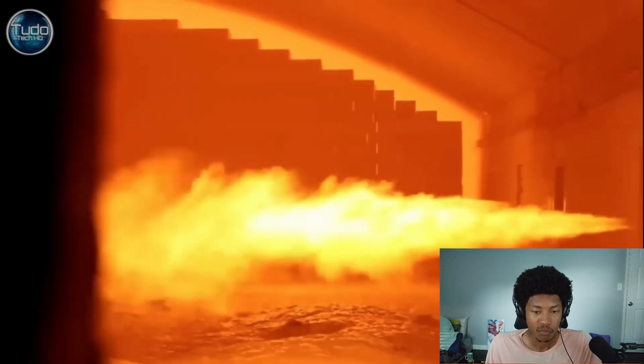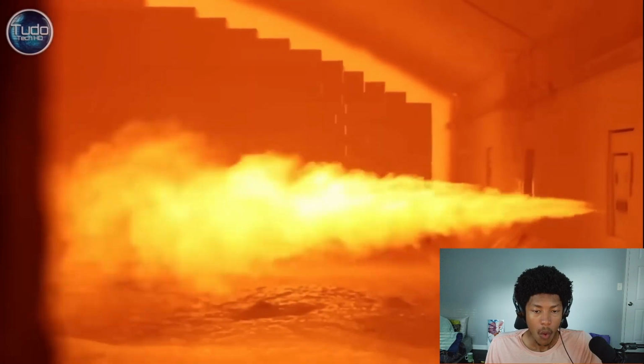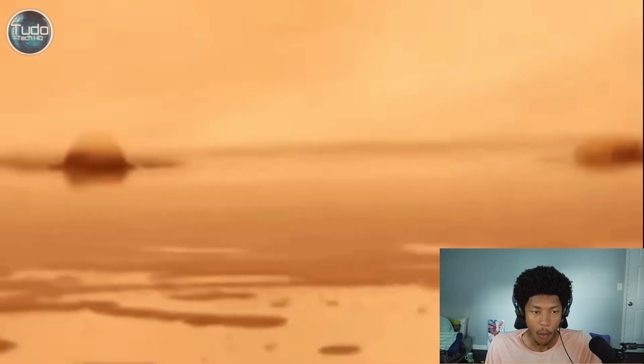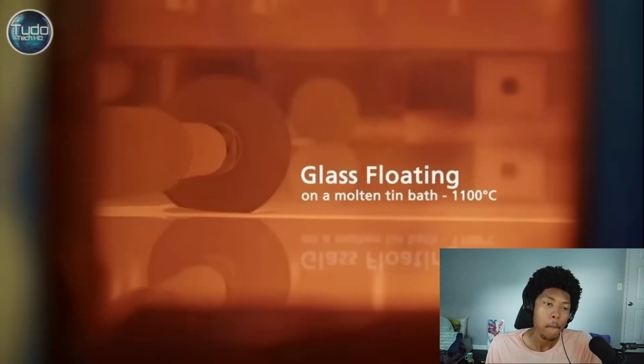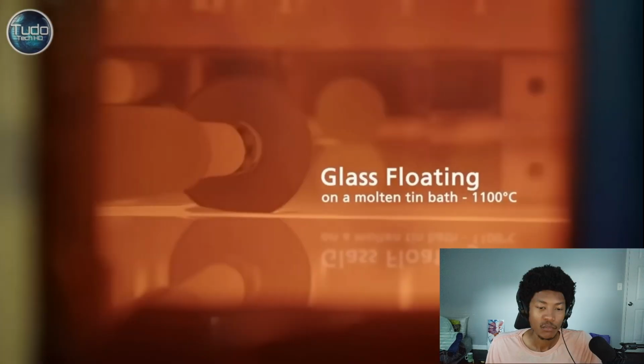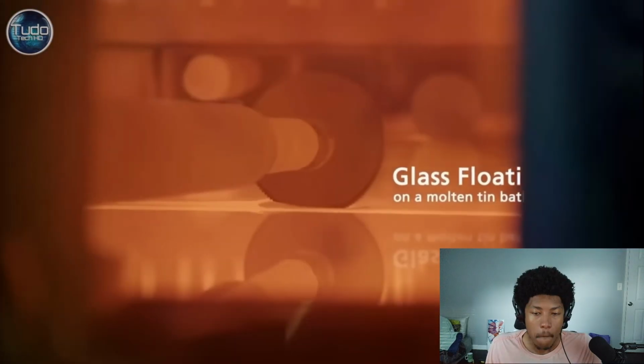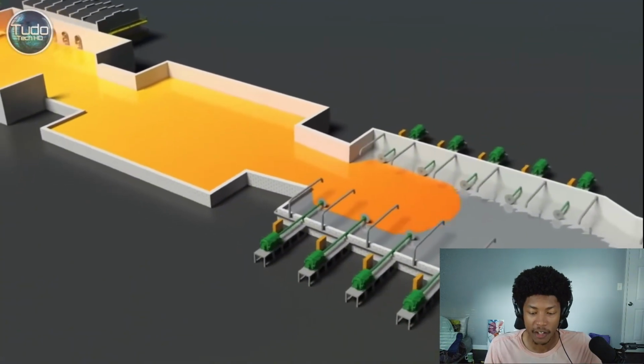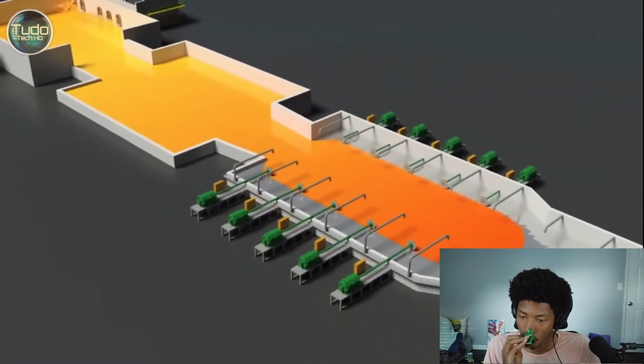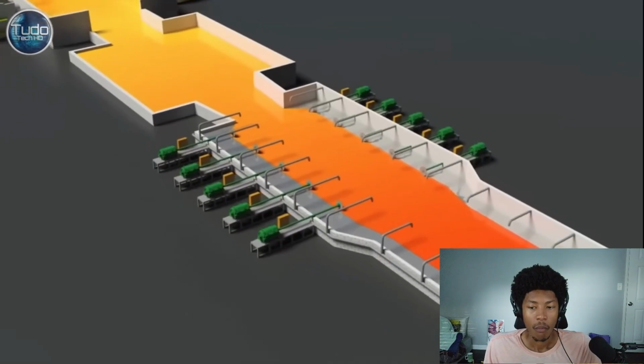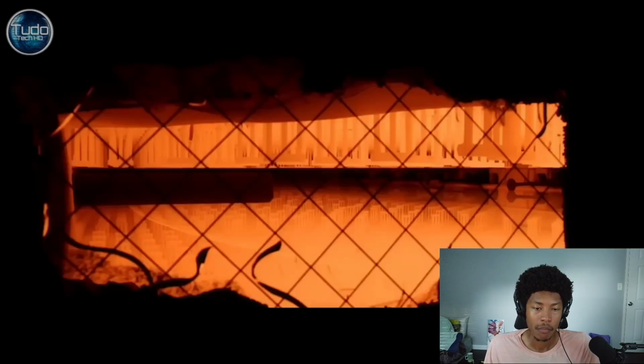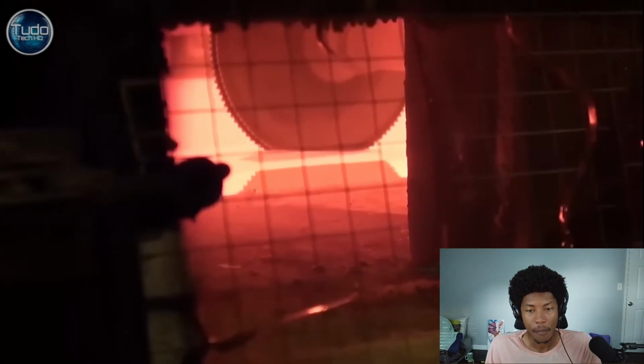The natural thermal agitation of the mass ensures a uniform glass composition and viscosity. Liquid glass at a high temperature, approximately 1,100 degrees Celsius, flows over a bath of molten tin. This process occurs in a protected environment filled with gases such as nitrogen and hydrogen, which prevent the tin from oxidizing. Due to the difference in density, the glass naturally floats on top of the tin,